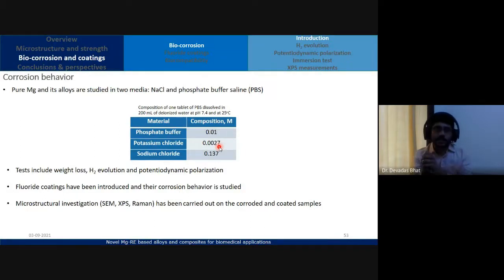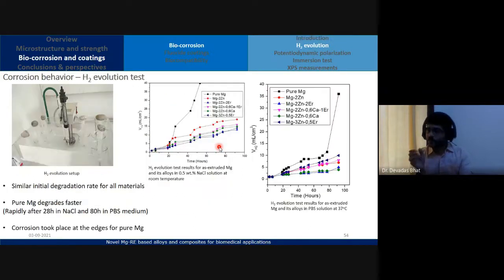That's the immersion test. So you do it for 1 day, you do it for 3 days, you do it for 7 days, and then you can study the evolution, how the corrosion rate, or rather how much degradation in weight percent takes place. Hydrogen evolution, like I said before, let me show you a particular setup here.